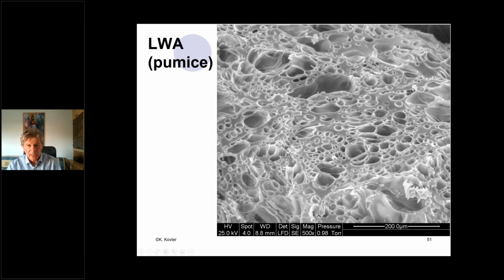This is an electron micrograph of the typical structure of pumice. We worked a lot with pumice. In the beginning of the 2000s, I tried to introduce pumice as a good combination of mechanically strong aggregate, which is not disintegrating during mixing. Otherwise, if you use very weak but very porous aggregate, we tried to use, for example, perlite or some other very light porous aggregate with a lot of porosity, but very weak mechanically.